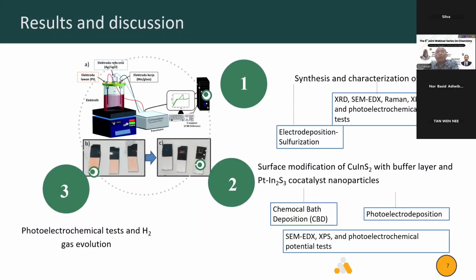Actually, after copper indium sulfide has been formed, we have to wash with KCN, potassium cyanide, to remove the copper sulfide that still exists in the material. So after that, we will have copper indium sulfide, and then we characterize using XRD, SEM, EDX, Raman, XPS, UV-vis DRS, and photoelectrochemical test.